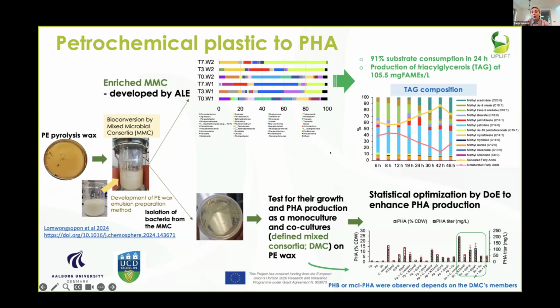And again, this now could become a very amenable feedstock for a range of bacteria, including the ones that are producing polyhydroxyalkanoates, because feeding fatty acids to PHA-producing bacteria is the best way to get a high titer of polyhydroxyalkanoates. So one of the consortia was used to produce PHAs, and that was recently published. And if you want to read more about the process, and especially about design of experiments where we try to find optimal conditions, how much and how to feed this PE wax to produce PHA, you can find it here